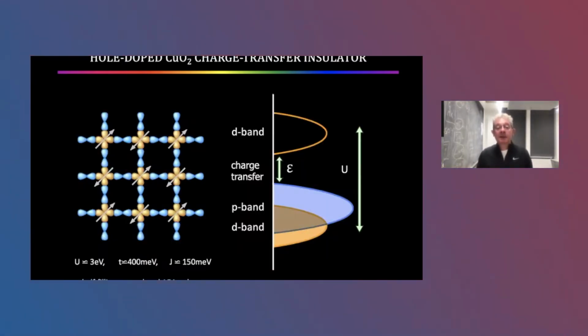Now let's think of the electronic structure. So the CuO2 plane is a square lattice of copper, oxygen, copper. The coppers are in the 3d9 state. To put them in the 3d10 state requires a Coulomb energy, U, which is about 3 electron volts. The overlap integral of copper and oxygen makes what would be a hopping rate of around 400 millivolts. It's a very strong overlap integral.